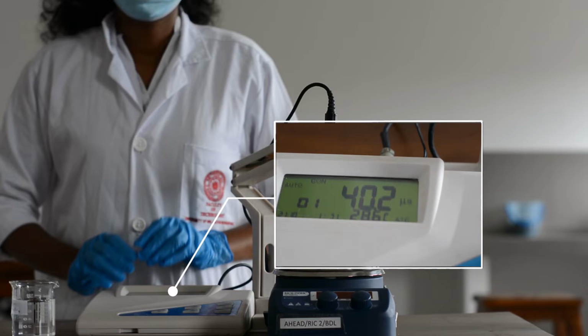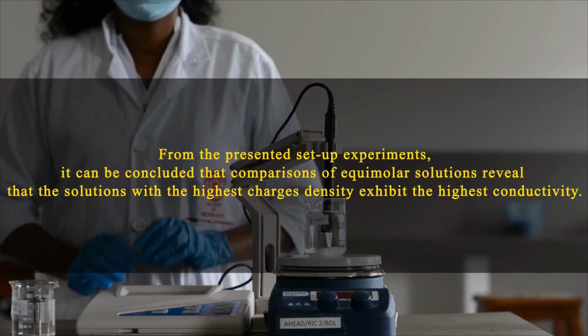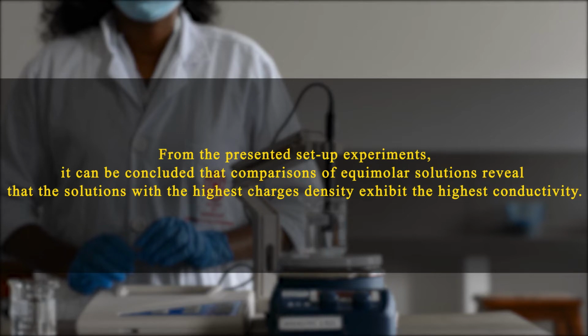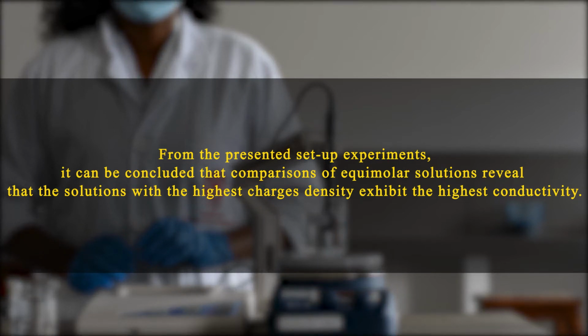And now the last sample, conductivity recorded as 40.2 microsiemens. From the presented setup experiments, it can be concluded that comparisons of equimolar solutions reveal that the solutions with the highest charge density exhibit the highest conductivity.